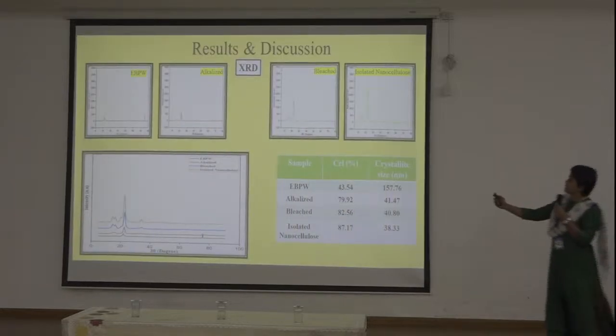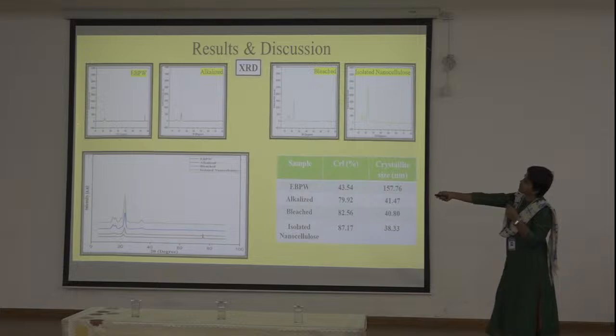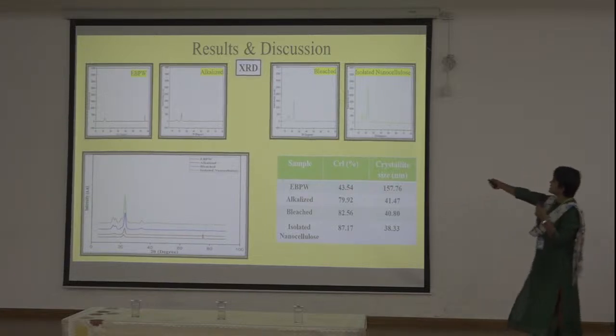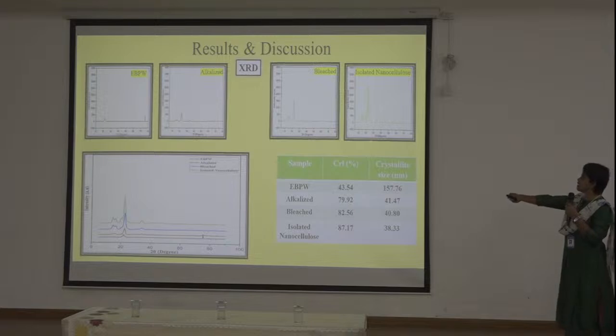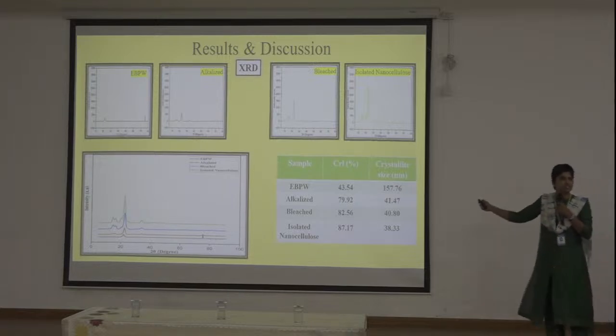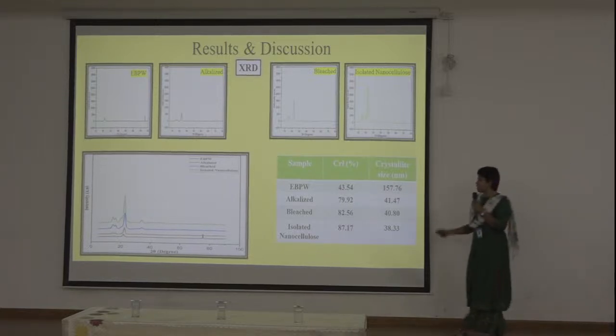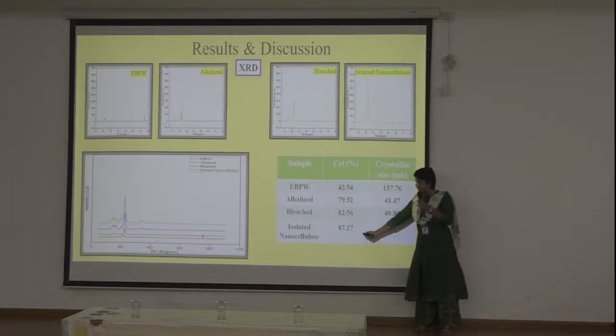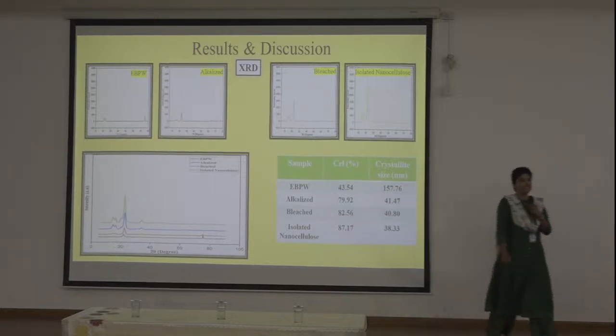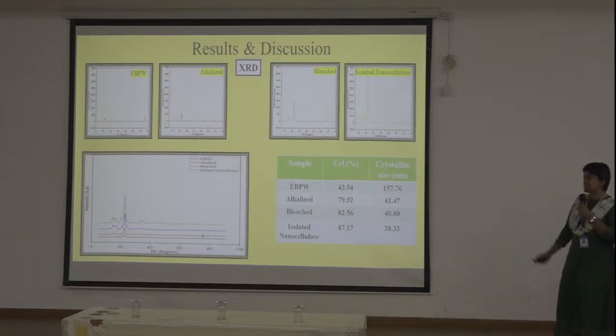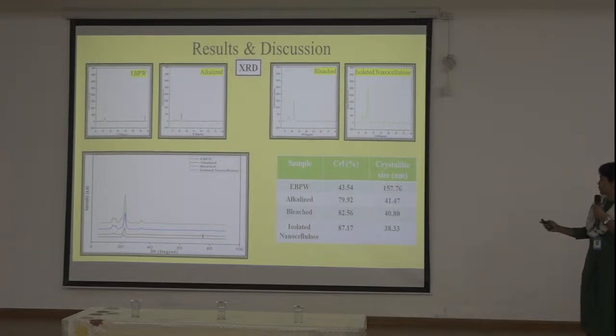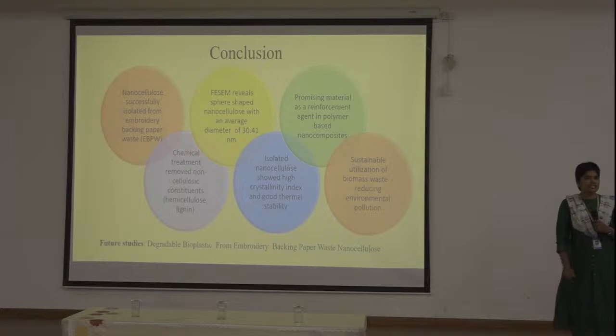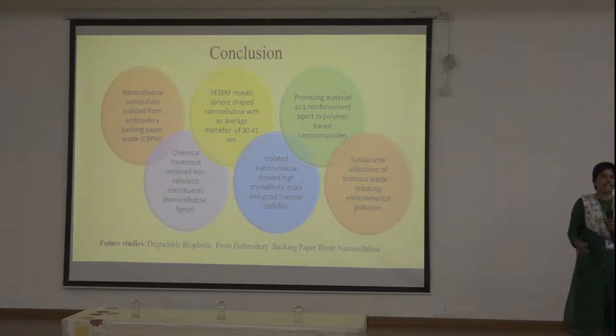For the XRD result, you can see that in embroidery backing paper waste there is less peak, but as the treatment progresses the peak increases, and the isolated nanocellulose shows a sharper and higher peak. This shows the crystallinity index of the nanocellulose, and the isolated nanocellulose showed a crystallinity of 87.17% and a crystalline size of 38.33 nm.